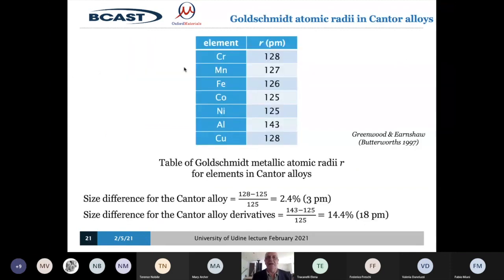So let me first of all just put a bit of flesh on the bones of that. The first 5 elements here are the 5 elements of the Cantor alloy. We won't talk about the other 2. Their radii are given there, so-called Goldschmidt radii. The rough size difference between them is 3 picometers. It's about 2 to 2.5% difference in size between the different atoms. So what that means is that there's about a 2% stretch in the lattice locally. That's quite high forces locally. 2% strain in a material leads to quite high forces. So the lattice not only has all sorts of different environments, it's got different stretches and distortions inside it.